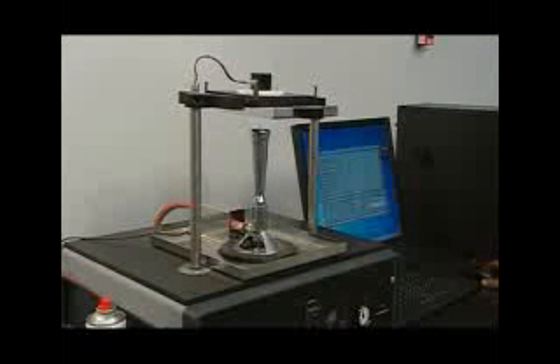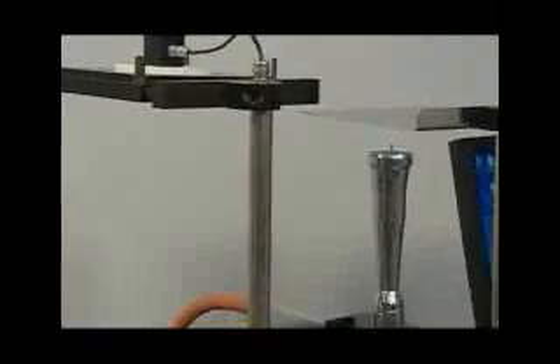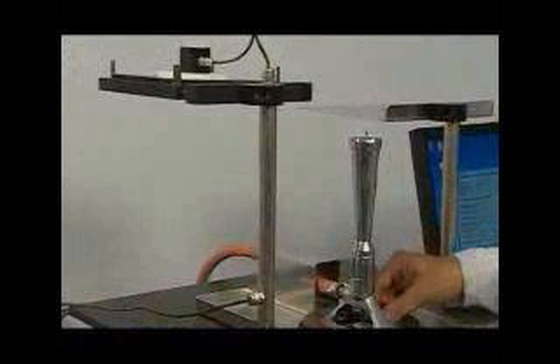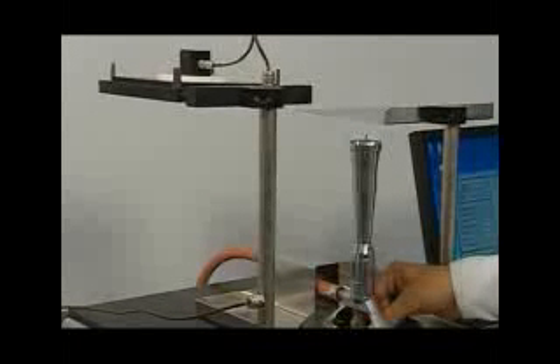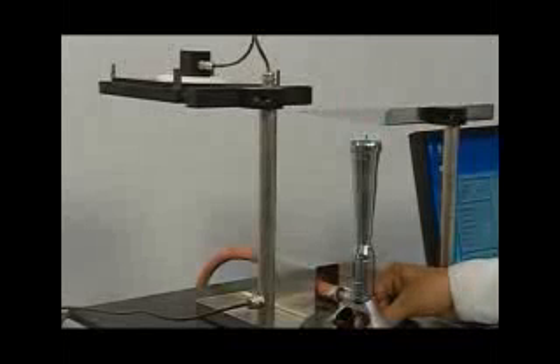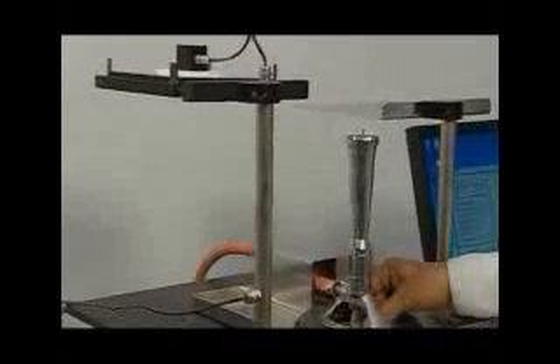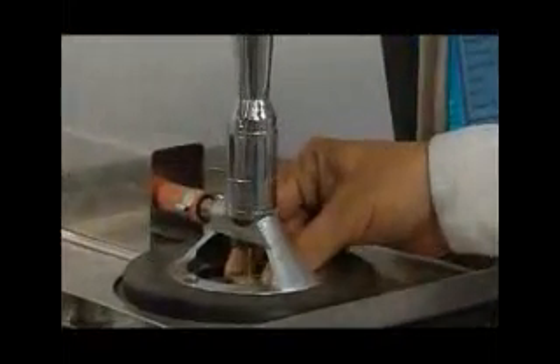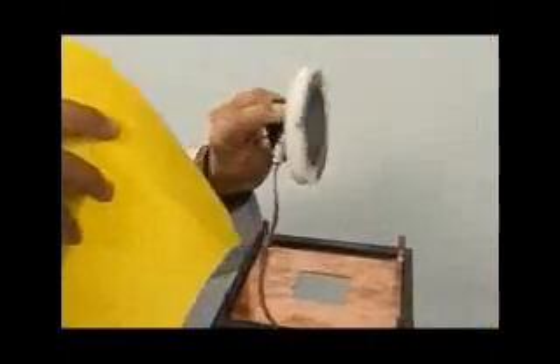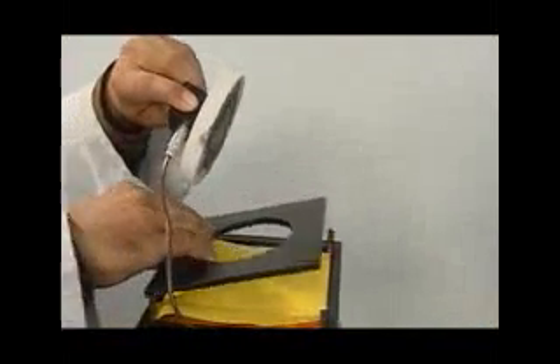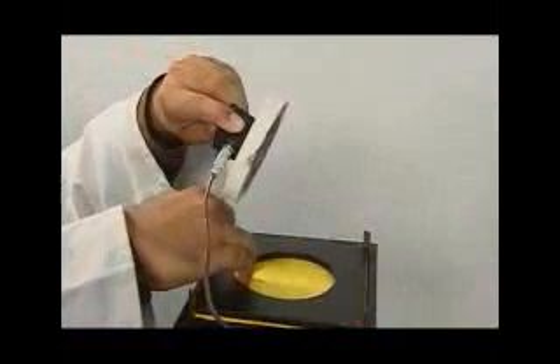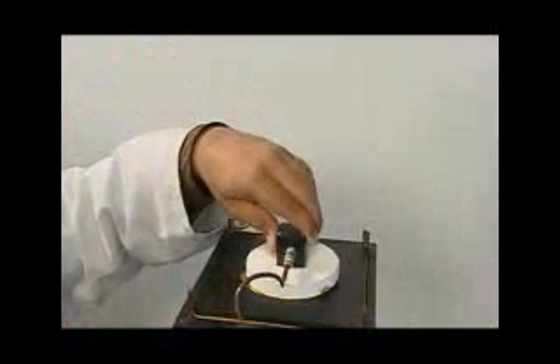The heat passing through the specimen is measured by means of a small copper calorimeter on top of and in contact with the specimen. The time in seconds for the temperature in the calorimeter to rise 24 plus or minus 0.2 degrees Celsius is recorded. The mean result for 3 test specimens is calculated as a heat transfer index, which is called HTI. For better understanding, let us see how the test is performed. Specimen is placed on the support frame and the copper calorimeter is placed on the top of the specimen.